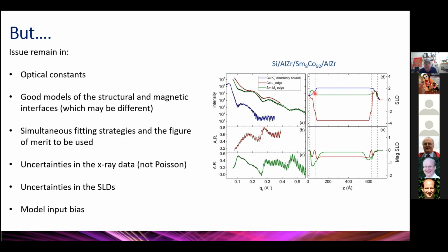So if you think of how we normally model an interface between a slab A and a slab B, we put an error function through it, or some such profile. How you profile something which is going in one direction positive and in the other direction negative, and making that self-consistent across the different energies, I think is one of the areas where a lot of this falls down.